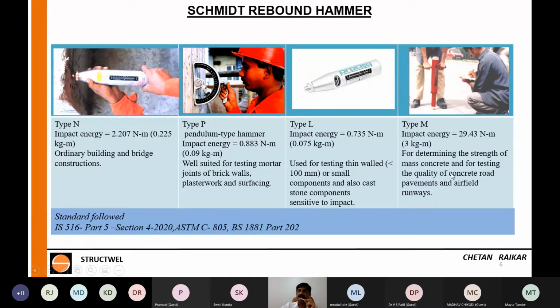For determining the strength of mass concrete for roads and other thicker elements, you know, foundation tops, pile cap tops and things like that, you can see the height. See, this Schmidt hammer is approximately a foot long, whereas this Schmidt hammer is 3 feet long. So you can see the difference in impact energy also. This is 2.2 Newton meter, and this is 29. So it's almost 10 times, a little more, you know, 13, 14 times higher.